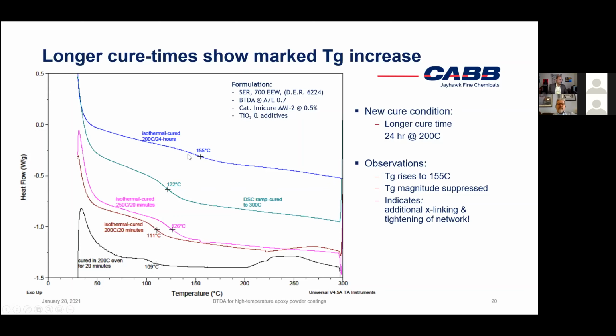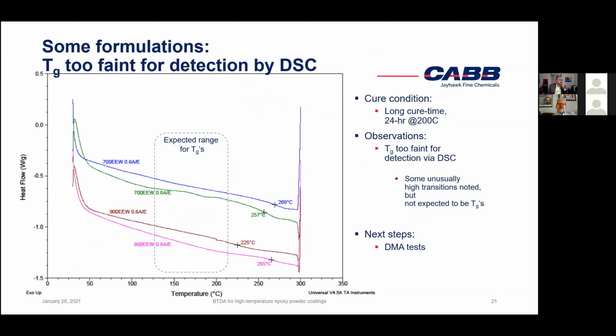And then the other thing we notice is that when properly cured, these systems will have a relatively faint glass transition, not only high, but very faint. In fact, this was the case for most of our formulations from the study. When these formulations were cured for 24 hours at 200C, some of the other formulations didn't even give us a DSC TG. This is the range we expected, and we didn't see the TGs. So we knew that we had to do DMA tests to be able to at least make out the TG when you cure it to that extent. And we did do that.